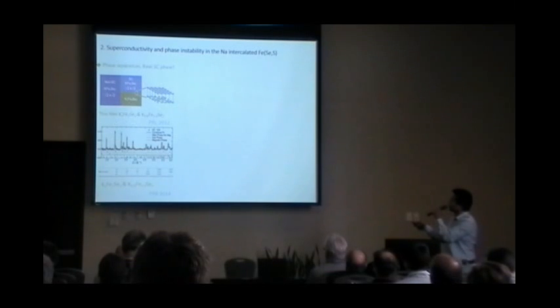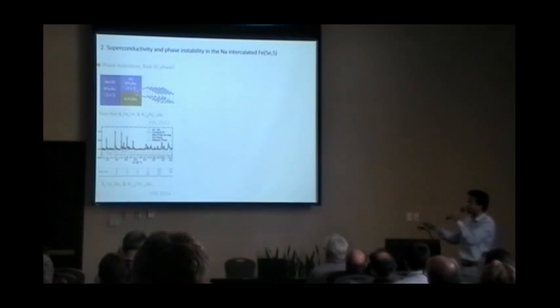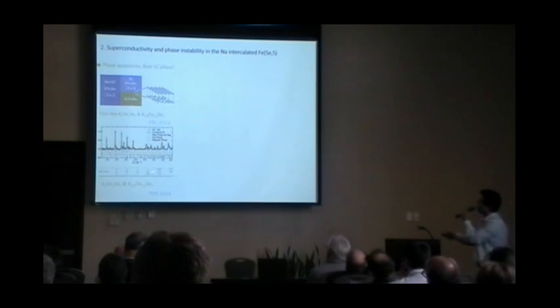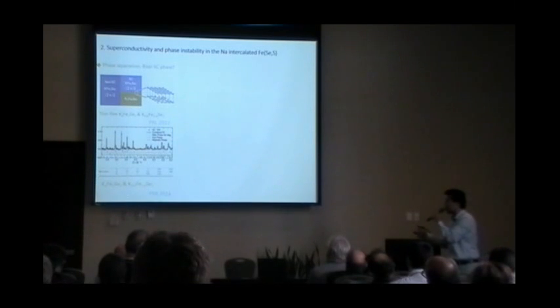So this is the same film. We can see that even in the same film, there is a mixed phase. One is the so-called 1-2-2 phase, another is the 2-4-5 phase shown here. This one should be the real superconducting phase. This one is just a semiconductor. From the bulk sample, they also got a similar result.